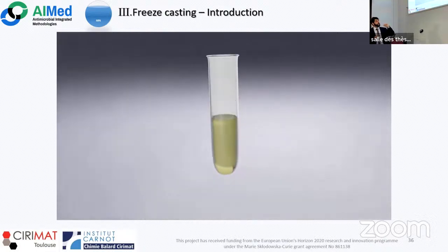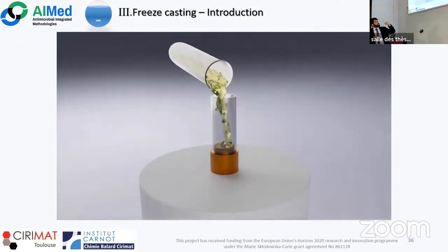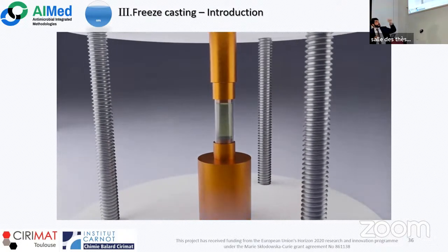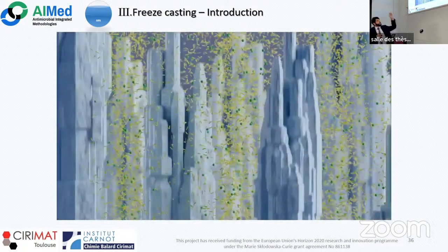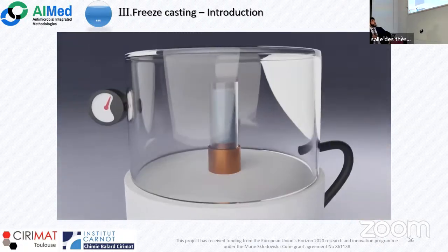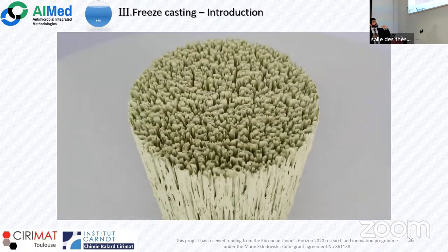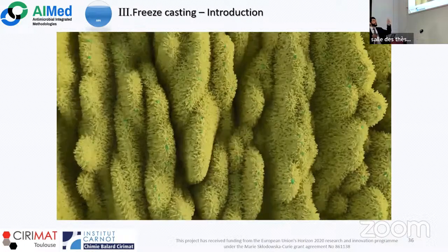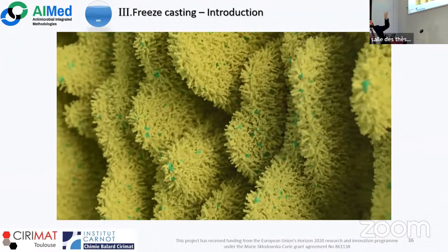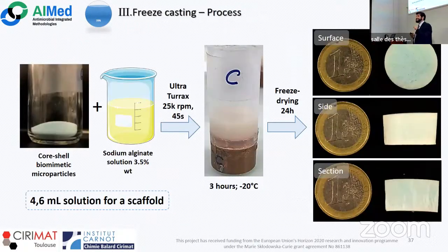That is fundamental because, as you can see in the video, we prepare the alginate solution. We mix and homogenize it with the particles. Then we pour it in our mold and we place it in our prototype to freeze it from the bottom to the top, and to obtain a well-frozen structure that is then freeze-dried and shows an interesting oriented porosity because of the vertical crystal growth that happens in the technique. So in our case, we use 4.6 milliliters of solution to obtain our scaffolds.